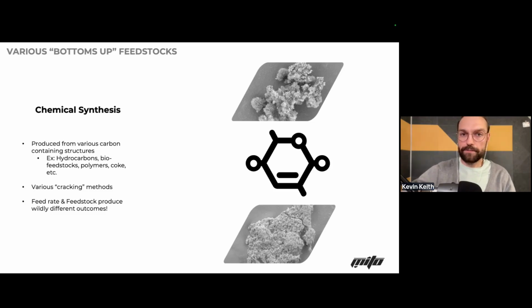Now, the various cracking methods that can be used to blow these apart to have these carbon allotropes reform into themselves. There's pyrolysis, essentially controlled explosions using, I don't know, anything like a spark plug within an inert environment with a little bit of oxygen to control that explosion. Plasma reactions, so using microwaves to have a really high heat, high throughput system that you can start pulling levers on what inert gases you're using within that plasma process, your feed rate, your heat, to have a monolayer come out the other side, carbon black. It's a very wide range of what you can do with that.